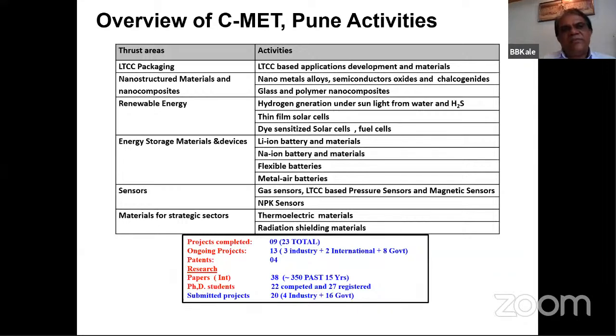The hydrogen storage problem today is that unless we have around 6% by weight, or 6 to 7%, it is not feasible, because if you have very low, then the amount of material goes up, and that will not be feasible. So people are trying whether we can get 9% to 10% or 11%, something like that. Then it's very easy to store hydrogen, and we can use this hydrogen storage material for automobile applications. Suppose you want to run the bike.